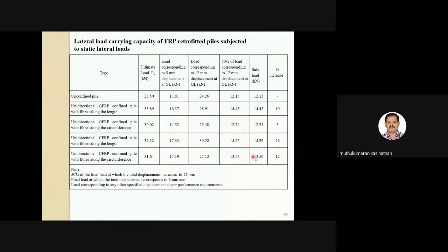So after retrofitting, we are able to bring back the safe load of 12 kilonewton or slightly more than that. You can see here, even by using glass fiber in the circumferential direction, we are able to get a 5% increment in the failed pile. So that means a retrofitted pile using glass fiber or carbon fiber has slightly higher capacity, almost 26% more than the actual conventional pile. That very clearly shows this particular FRP strengthening process is very well suited where your piles have failed, that means failed but in a repairable condition. Where it has reached a repairable condition, you can retrofit those kinds of piles using this FRP method.